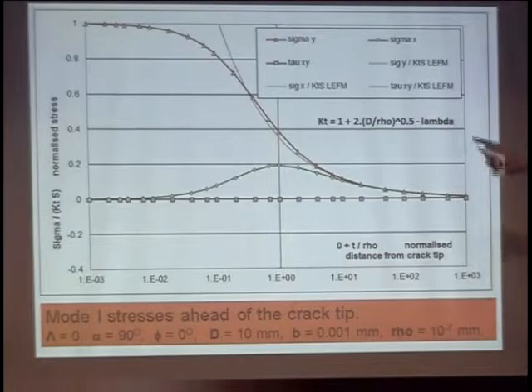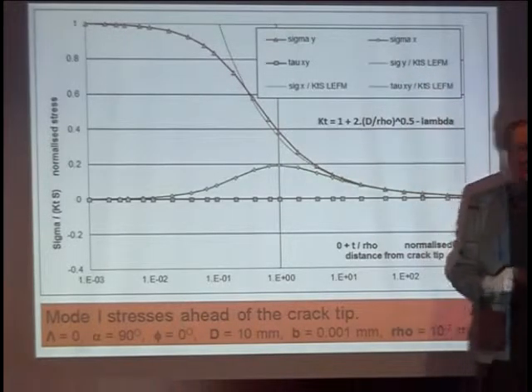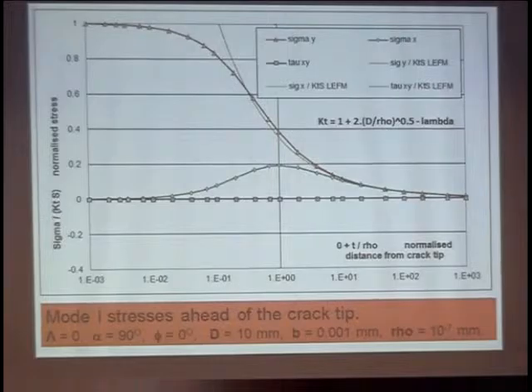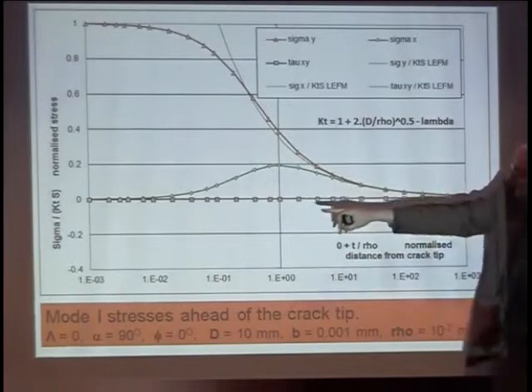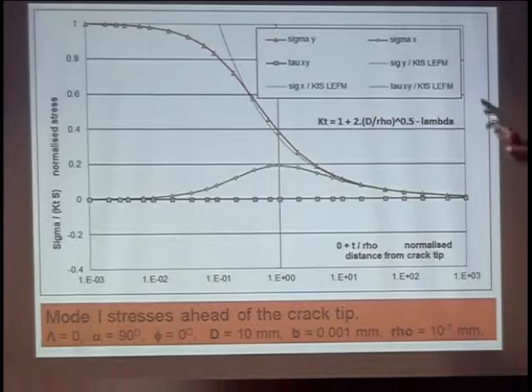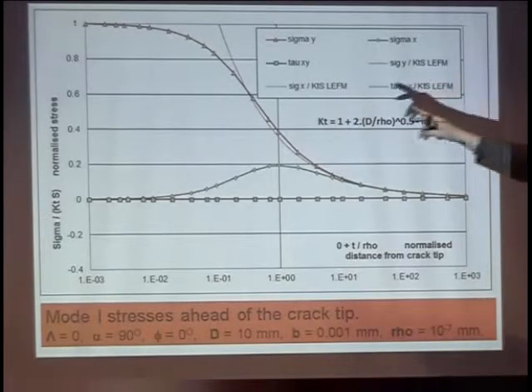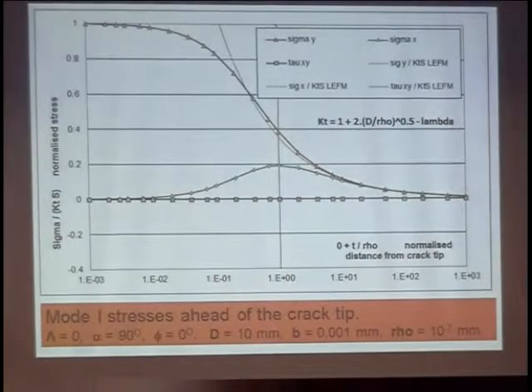Vertically, the stresses: I've got sigma x, sigma y, tau xy, Cartesian axes, y is normal to the crack and so on, and they're all plotted here. And then we normalise by k_t sigma, where k_t is this formula. So when you get to the crack tip, of course, mode 1 stress gets to unity, which you see up here at the top left-hand corner. The dotted line is the fracture mechanics solution. It's the usual result that goes off to infinity when you get to the crack tip.